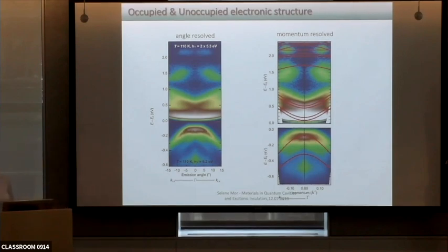What I can tell you is that definitely the dynamics of the hole population and of the electrons in the conduction band are really different in time scale. So the conduction band is depleted much, much faster. Where the electrons go, who knows? So in that sense, they definitely have different characters, and whether this can be enough to describe the momentum dependence of the gap, I'm still not sure. Because in their case, they use absolutely symmetric bands, and that actually was the mechanism giving the widening that we observe.